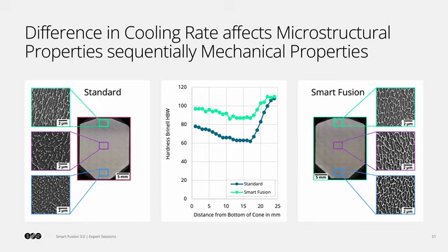A hardness profile from the bottom of the sample to the top has been used to exhibit change in mechanical properties and its homogeneity. The standard sample showed an average lower hardness and exhibited more significant variation in hardness as the distance from the bottom of the sample increased.